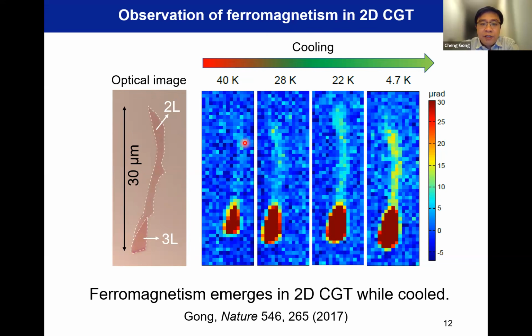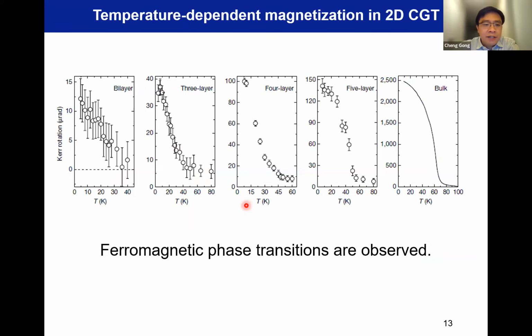At 40K, you see the signal is already gone, but the 3 layers still have very clear signal. So this indicates a clear thickness-dependent TC. The thicker sample may have a higher TC. So then we do the systematic study for different thickness, tri-layer, 4-layer, 5-layer up to bulk. For each one, you scan, you measure the temperature-dependent Kerr rotation. You can then extract the thickness-dependent TC.